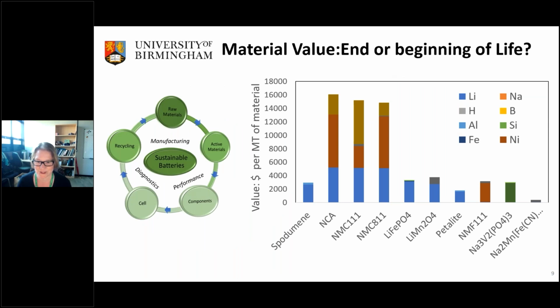And one of the things I wanted to show here is the value, or the cost of the metals that are contained within some of these materials. On the left-hand side, I've got a range of lithium-ion cathodes. Spodumene is a primary ore. And then we've got some cathode materials, NCA, which is nickel, cobalt, alumina, the NMCs with different ratios of nickel, manganese, and cobalt. We've got lithium iron phosphate, lithium manganese spinel. And you can see, I found this very interesting, that there's actually more value in our cathode materials in terms of lithium, which is the blue bar at the bottom, than in some of our primary ores, such as spodumene.